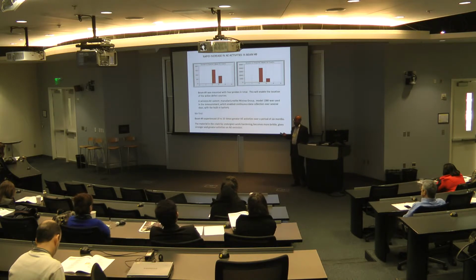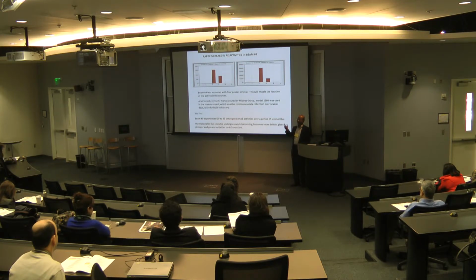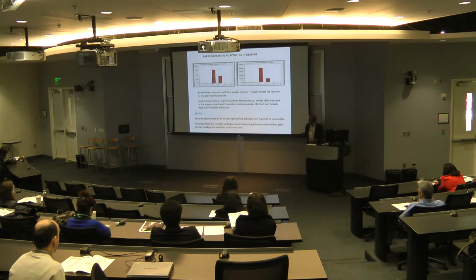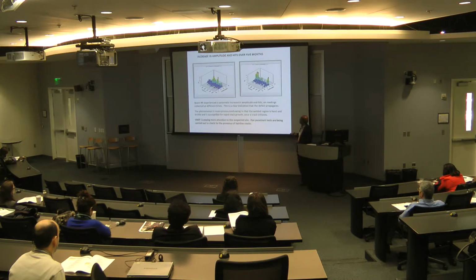Conventionally, these tests are carried out by VDOT people, the transportation people, by visual examination. It is very subjective, and due to human fatigue, they may fail to notice some of the defects. But with AE instrumentation, we thought of using it so that the test result can be automatically projected to indicate what the defect is, where the defect is, etc. Since we have got these results, VDOT is carrying out a dye penetrant test in the suspected area to look for the presence of hairline cracks. This is again a comparison of what was detected in September and what is being seen now, and there is quite a considerable increase in the amplitude.